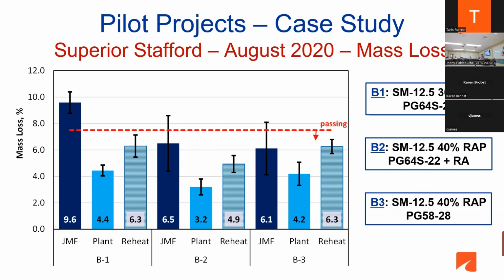And you see that your mass loss decreased for the 40% RAP B2 and B3. That tells me that these mixes will have a similar or better durability than the control mix because they are engineered. That's expected. We've seen a similar observation at the plant. So that's the light blue in the middle. These samples we took right away at the plant, we compacted, and then we tested. And then you have the shaded blue, the third one, where we collect mixtures, take them into our lab, and do some extensive additional testing. We had similar observations: a similar or better durability. The lower the value, the better the performing mix. That tells us that durability-wise, we put in a little bit of recycling, but we didn't jeopardize durability. So we're good in terms of that.